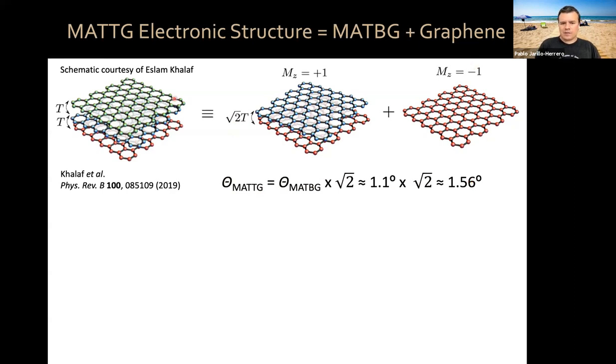This decomposition, block diagonal of this electronic structure, means that in the situation where you have this mirror symmetry, you get this for your electronic structure. By the way, if you remember, for magic angle bilayer graphene, the Moiré wavelength was 13 nanometers. For the trilayer, because the twist angle is a little bit larger, the Moiré wavelength is a little bit shorter, about 9 nanometers. That likely means that the interactions between your electrons are a little bit stronger.